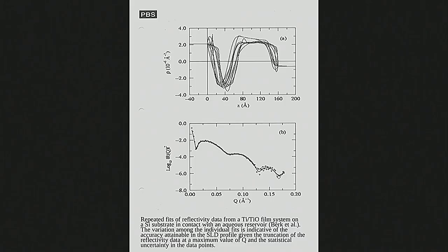Then there's a layer of titanium, and the titanium has a negative scattering density, which occurs for some of the elements for neutrons. So instead of being a positive scattering power, it's a negative scattering power. We won't go into details why. Maybe Roger Pin already talked about that. But then on top of that pure titanium metal layer is an oxidized layer, so it's titanium oxide, that was oxidized in an active electrochemical cell.